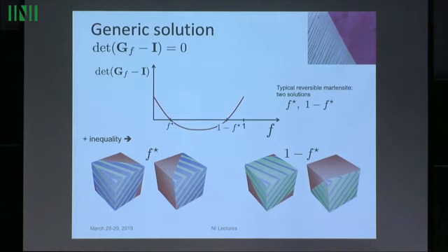If that's the case, then going back to the lemma, for F star, in fact, we have 2 solutions, because we had 2 solutions of that lemma. So it's a very similar situation. And for 1 minus F star, the other root, we have these 2 solutions. Once again, as I mentioned before, if you take one of these solutions, I don't remember which one it is, you compare with this picture, all the geometry agrees very nicely. The only point is about the fineness, and as I mentioned, all the geometry is predicted nicely by this calculation.